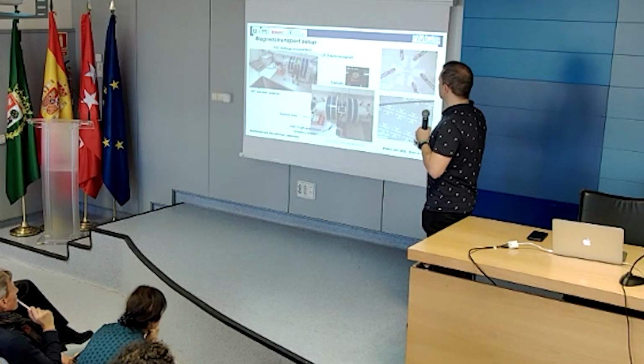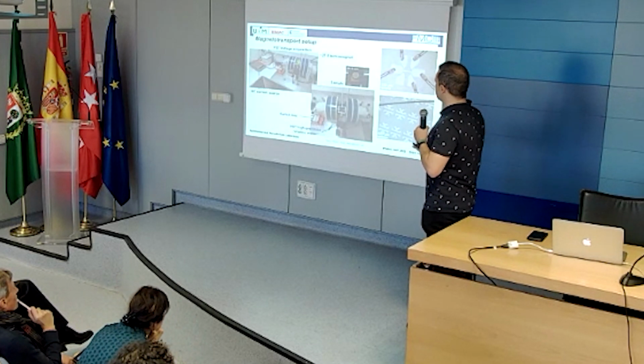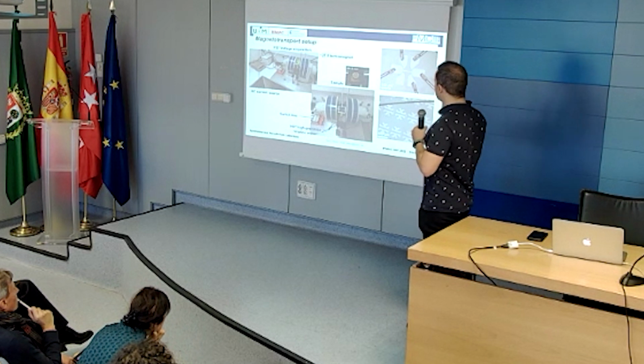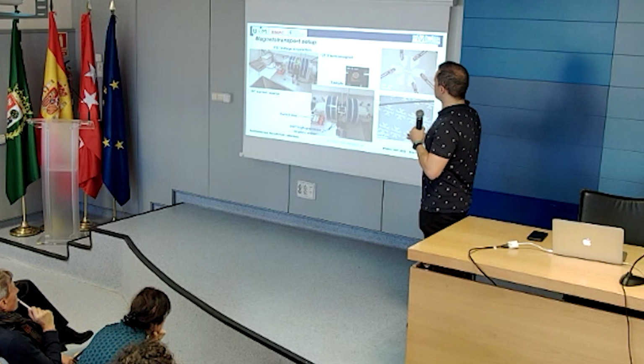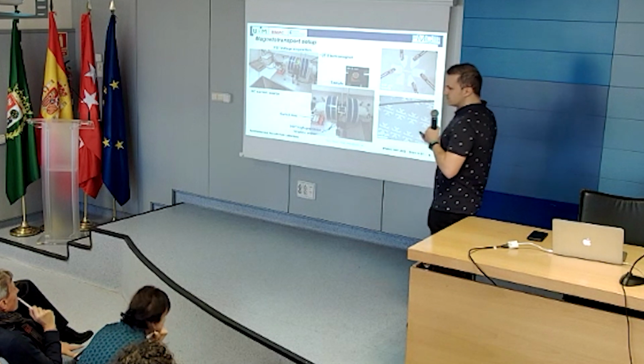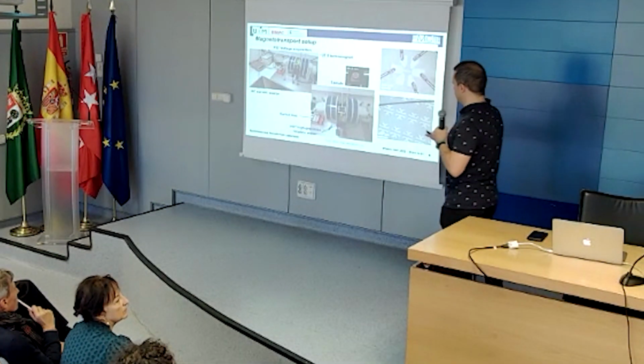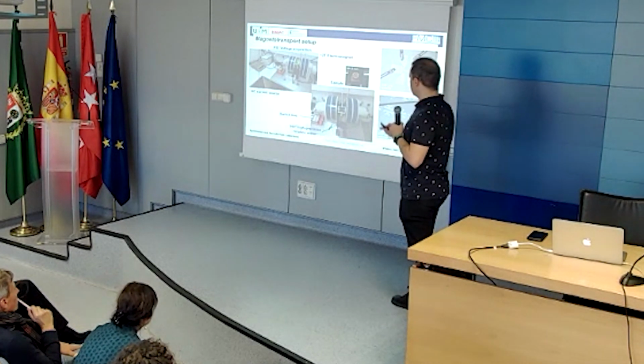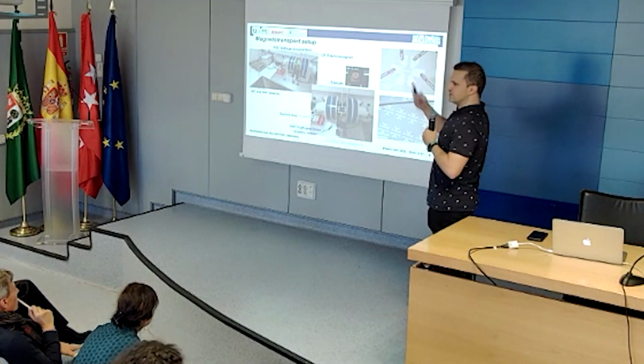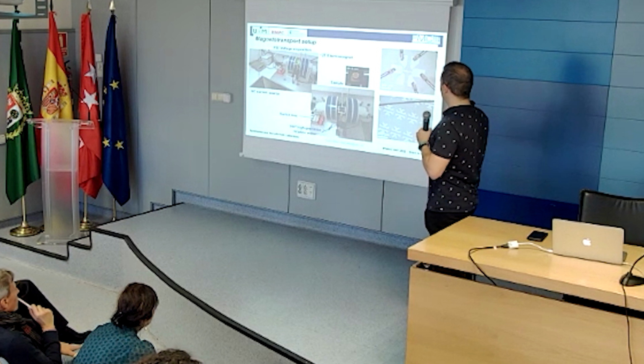So I can show you a little bit of what we are doing. We have a magnetotransport setup, so we can inject current with an AC/DC current source into our device that is sitting here. We have an electromagnet that can apply 2 Tesla, and this will record the voltage as we apply an AC current. We can take the measurements in continuous mode, and then do the analysis by computer.